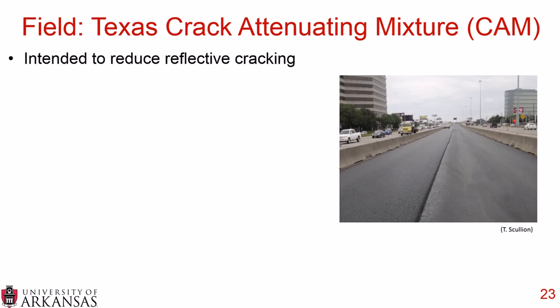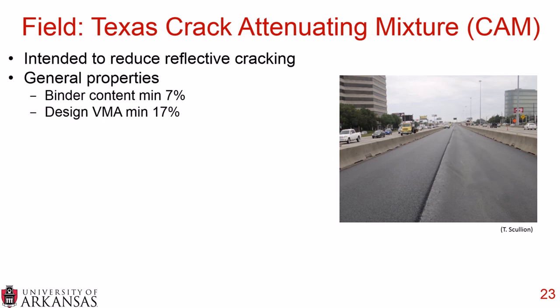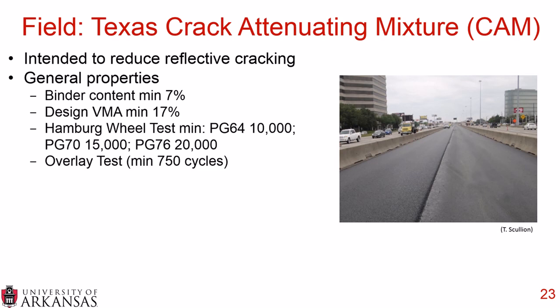Now in Texas, they have developed the Crack Attenuating Mixture, or CAM, and this is intended to reduce reflective cracking. Here's a nice picture provided by Tom Scullion. On the left-hand lane, you can see this CAM mixture. The general properties are a binder content at a minimum of 7%, and it's usually placed at 8%. The design VMA is a minimum of 17%. There's various Hamburg wheel test minimums based on the PG binder grade. If it's a PG 64 high temperature grade, it's a minimum of 10,000 cycles. A PG 70 is a minimum of 15,000 cycles, and a PG 76 is a minimum of 20,000 cycles.